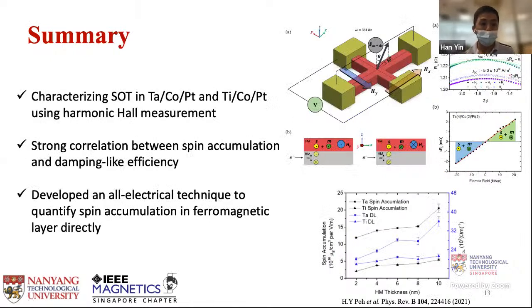So, in summary, we have successfully characterized SOT in Ta/Co/Pt and Ti/Co/Pt using harmonic Hall measurement. We also observe a strong correlation between spin accumulation and damping-like efficiency. Finally, we have successfully developed an all-electric technique to quantify spin accumulation in the ferromagnetic layer directly. This comes to the end of my presentation.